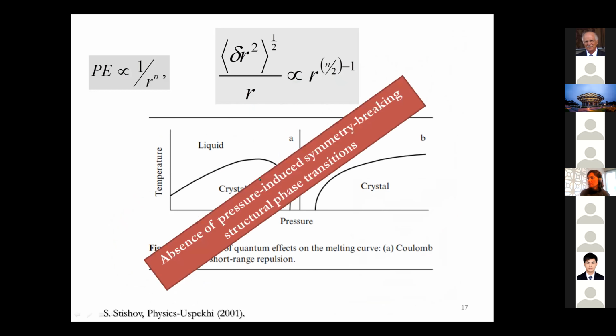Everything that I said was based on the fact that we only have solid versus liquid, and there are no other ways that the lattice can find an easier way to lower its energy. So we go from order to disorder and done. That's it. In fact, this is true only in the absence of pressure-induced symmetry-breaking structural phase transitions, that basically this kind of peak in the melting line can be assumed to be coming from the quantum effect.